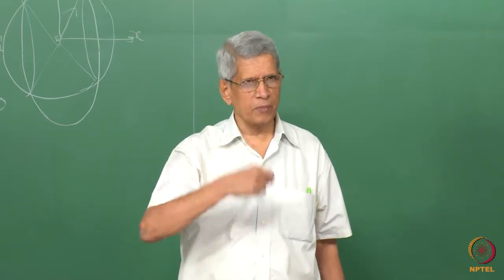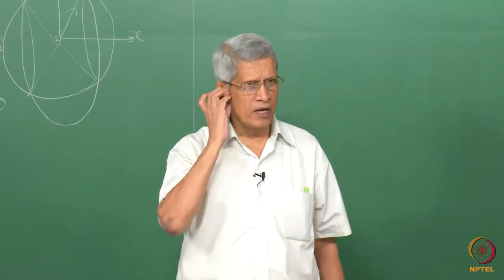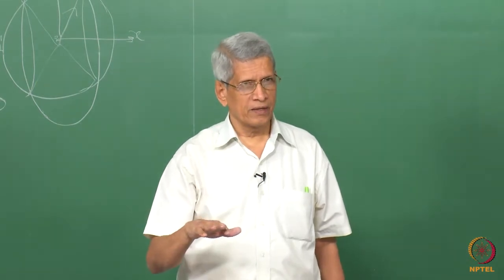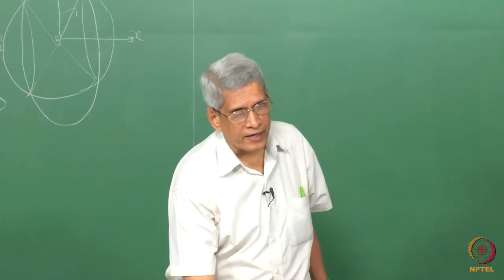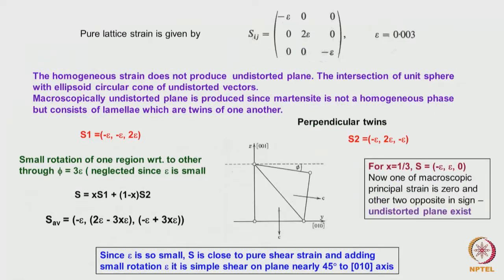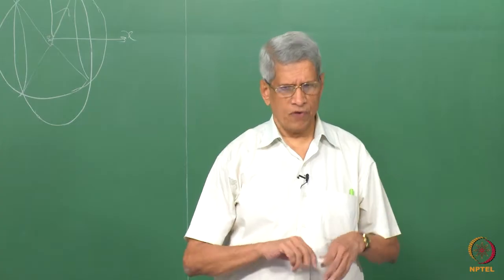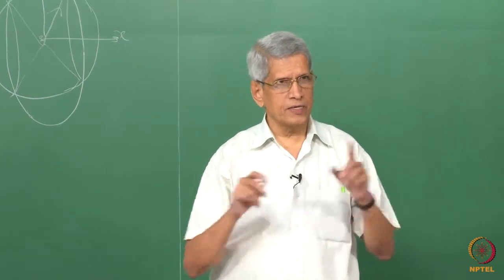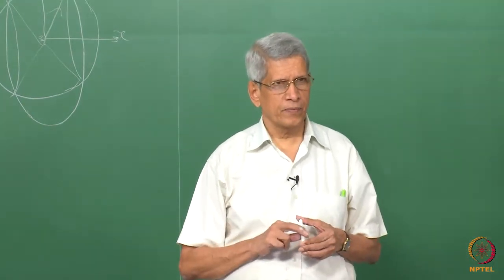In the third direction there may be a contraction or an expansion, but on one plane there is a contraction and expansion of equal and opposite magnitude. Here, we mentioned that 2/3 is the expansion and the other direction is contraction. If we look at the strain matrix, when the lattice has come from FCC, the strain is there in all three directions.